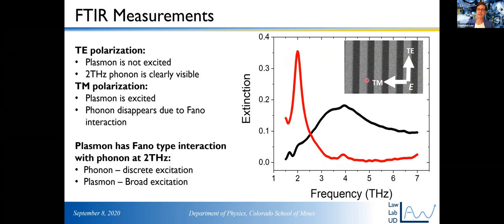However, if we polarize the electric field across the stripes like this, now we actually could excite a plasmon polariton. And what we see in the extinction data is this sort of broad peak here. What this is, and again, I'm not going to go into detail, but this is called a Fano interaction between the plasmon, which is basically here, and the phonon. You can see the 2THz phonon, which was the strongest feature, is gone. You don't see it at all in the black curve. And it's because of this special type of interaction that we have called a Fano interaction.